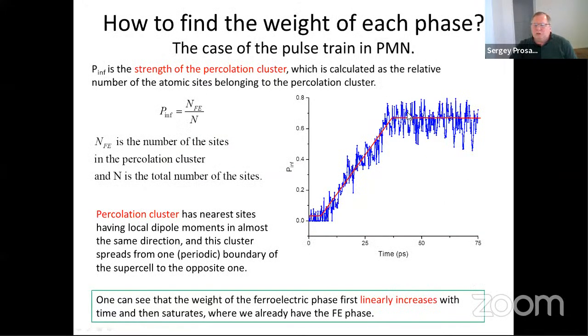This plot shows how to measure the occupation of different states, and we suggest using the percolation strength, which is the number of the ferroelectric ions in the connected cluster. And the connected cluster is the cluster which spreads from one boundary of the supercell to the opposite boundary, and in this cluster all dipoles look approximately in the same direction. So we see that the percolation strength approximately linearly increases and then saturates when we reach the ferroelectric phase.